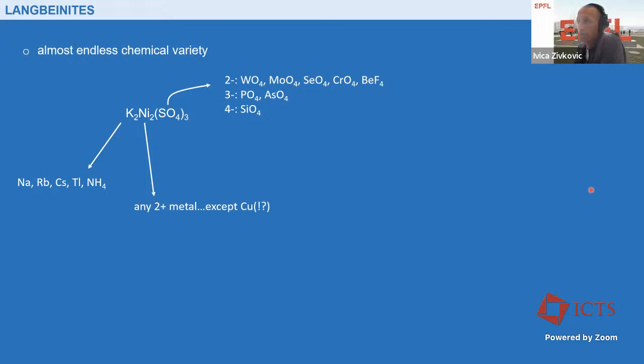And from the materials point of view, I think this family really offers an enormous potential. So potassium nickel sulfate, as a representative of quantum spin liquid behavior in a 3D regime, can be expanded in so many ways. You can change the alkali ion into all these ones. The 2+ magnetic ion can be changed into any other. Funny thing is that the copper does not work. For some reason, there are no reports of a copper version of the potassium sulfate langbeinite.